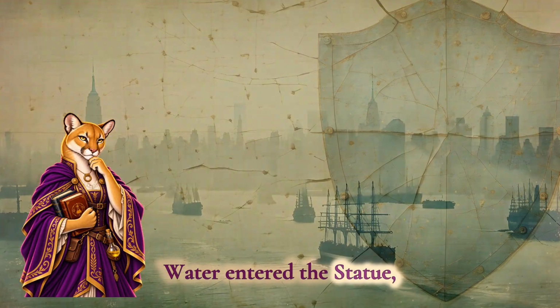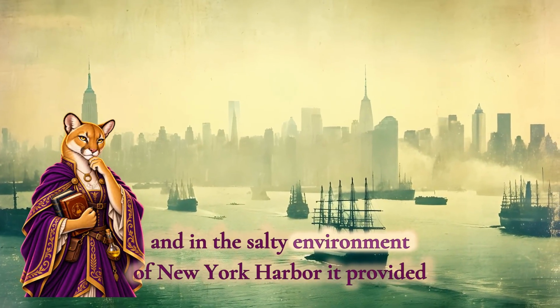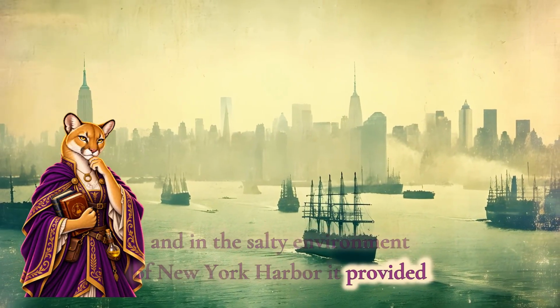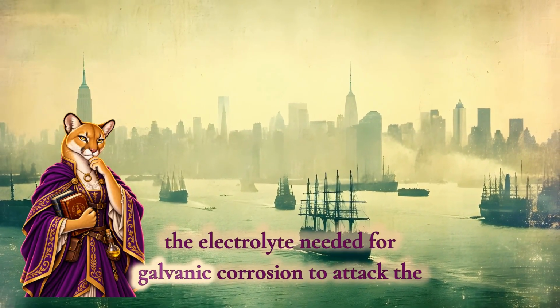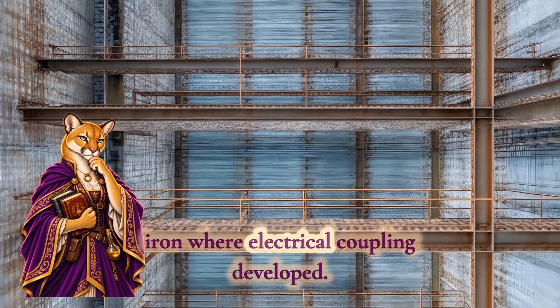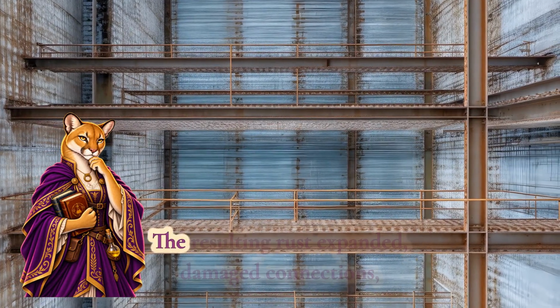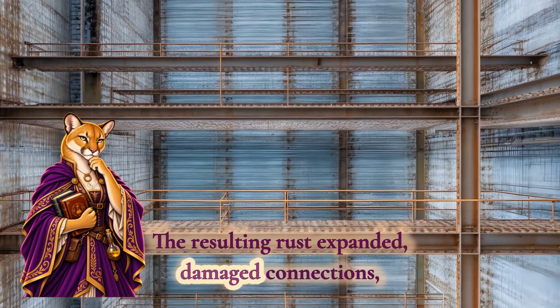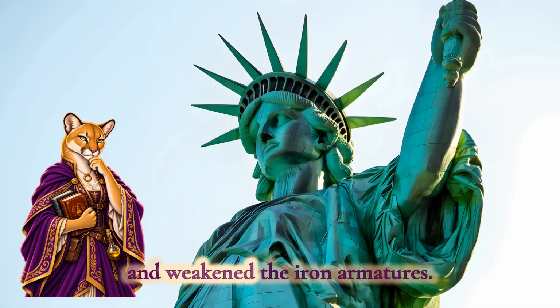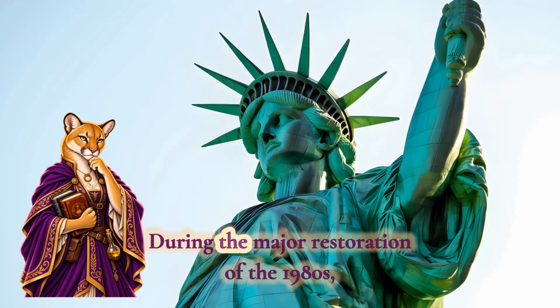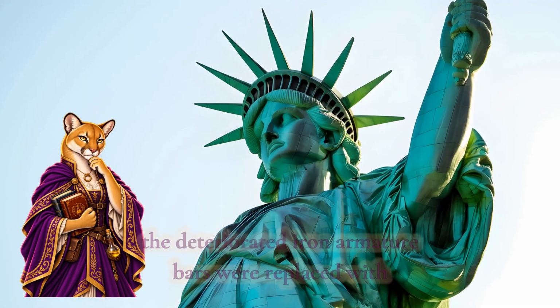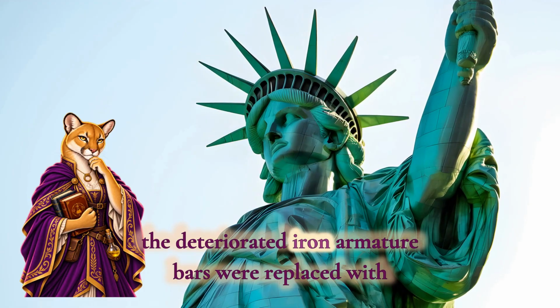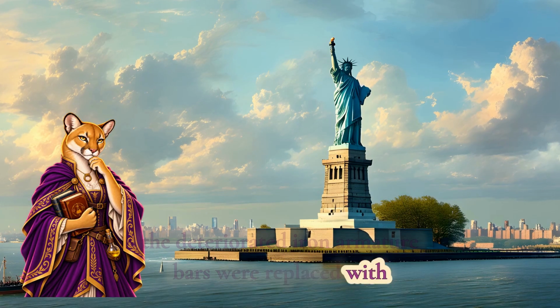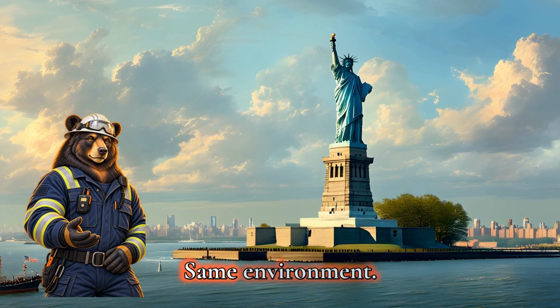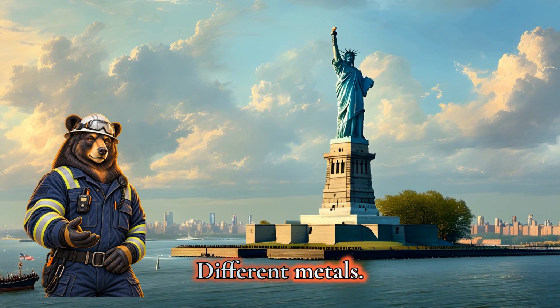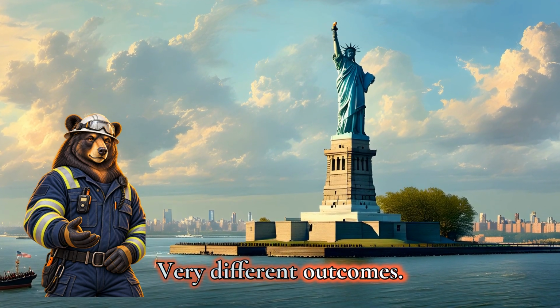Water entered the statue, and in the salty environment of New York Harbor, it provided the electrolyte needed for galvanic corrosion to attack the iron where electrical coupling developed. The resulting rust expanded, damaged connections, and weakened the iron armatures. During the major restoration of the 1980s, the deteriorated iron armature bars were replaced with stainless steel. Same environment, different metals, very different outcomes.